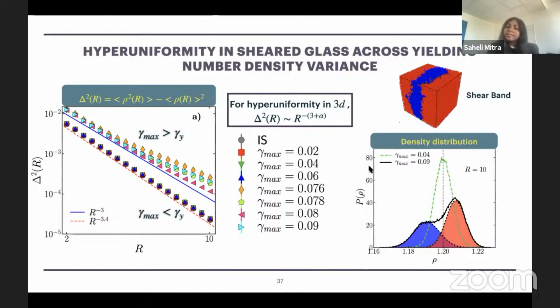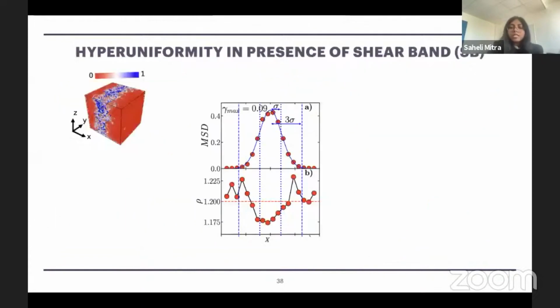We further analyze the system for the shear amplitude gamma max equal to 0.09 above yielding in the presence of a shear band. In the presence of a shear band, if we again do a color map of the particles from particle displacements from one cycle to the next, we can see where the shear band is located, and it is perpendicular to x. So along x, we can bin the system and plot the mean square displacement to locate the shear band exactly. The shear band is the part with high mobility. And if we compute the density of the system, we see that there is a dip in the shear band regime. That means the shear band regime has lower density compared to the parts outside. This result was already